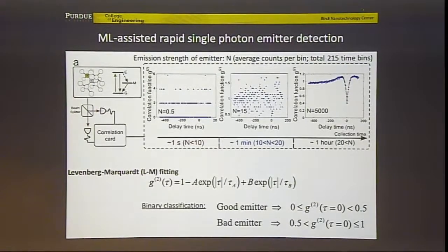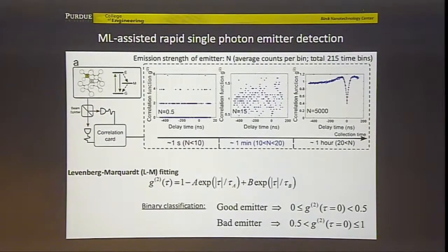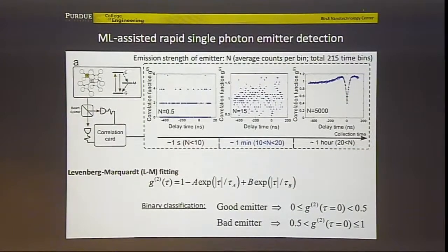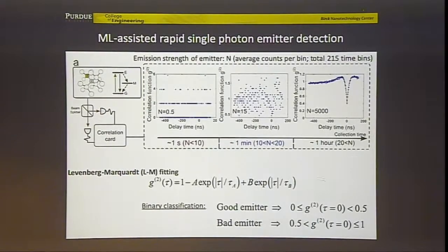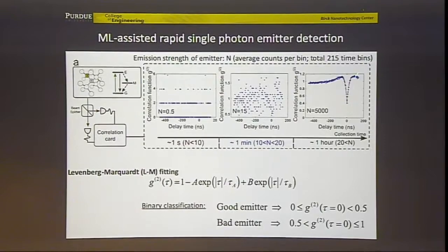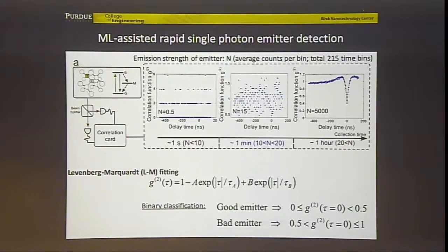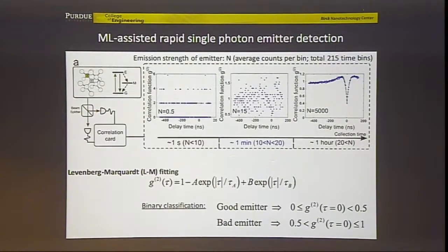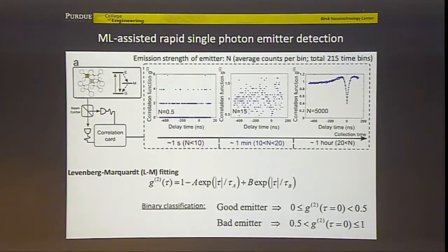And what people use is a rule of thumb. If it's below 0.5, this is a single photon source. If it's above 0.5, that's not a good single photon source. But to get this anti-correlation function, you use this Levenberg-Marquardt fitting, which is given by this formula. To get the fitting, you have to have lots of data points, many minutes of measurement and collection time. Then you get a good curve, you do this fit, then you take the correlation function at delay equals 0. And as I said, if it's less than 0.5, it's a single photon emitter. If it's larger than 0.5, it's not a single photon emitter.